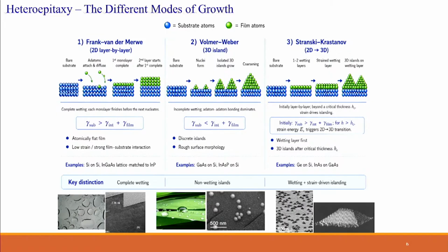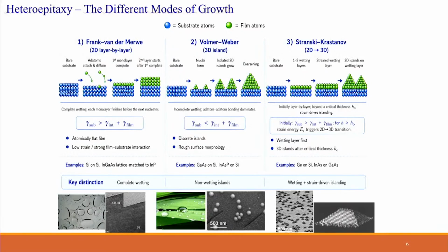Why? Because when you have such free surfaces, these can radially relax and release whatever lattice strain has been building up. This is not possible for a thin film like this. You have to have these truncated facets which can simply radially relax.